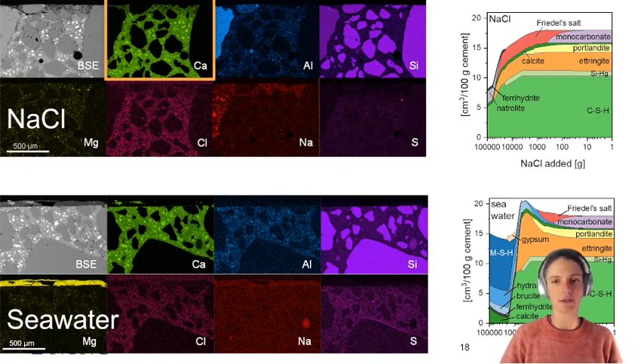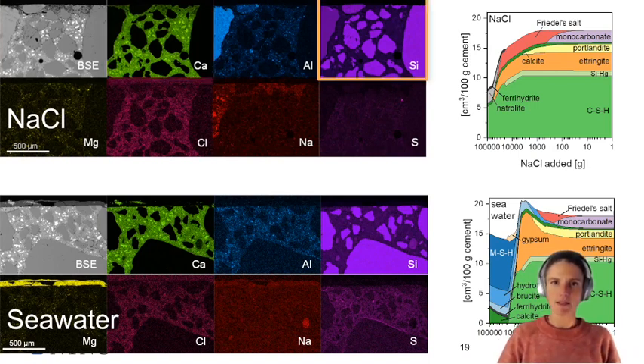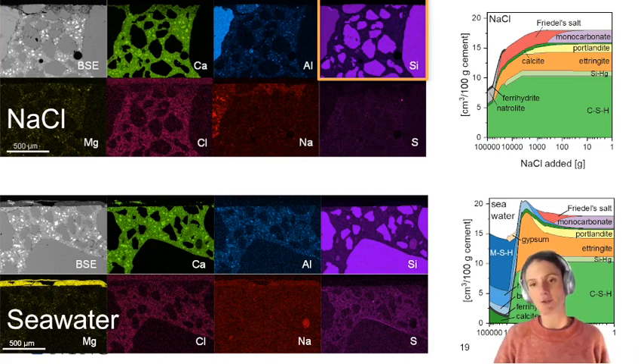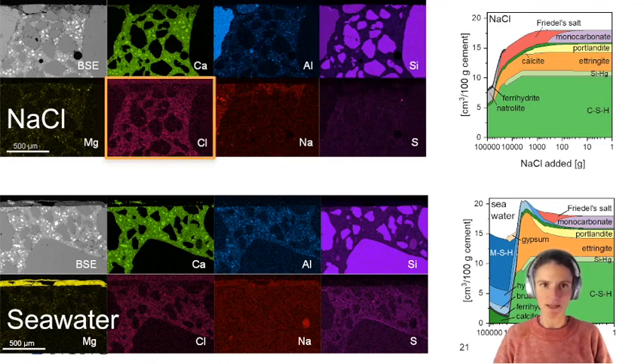So we are most likely having some leaching. There's not that much to see in the aluminium, so I jump over that. When we look at the silicon, this is a very nice illustration of what is sand. The sand particles I've used are very rich in silicon. So these are the sand particles, else there's not that much to see. Also for the magnesium, there's not that much to see in the sodium chloride exposed sample.